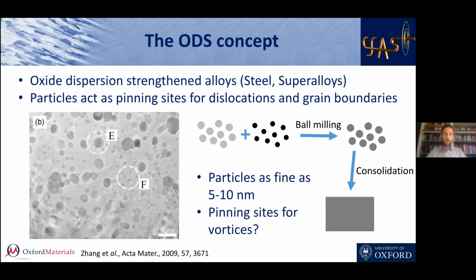And so the idea behind this was, can we take this concept that seems to work so well for materials that have strong mechanical properties, but instead of pinning dislocations or grain boundaries, which improve the mechanical properties in steel and superalloys, can we take these little particles and put them in a superconductor, here MgB2, and will they pin the vortices? And so by having extra pinning centers, can we improve the superconducting properties?